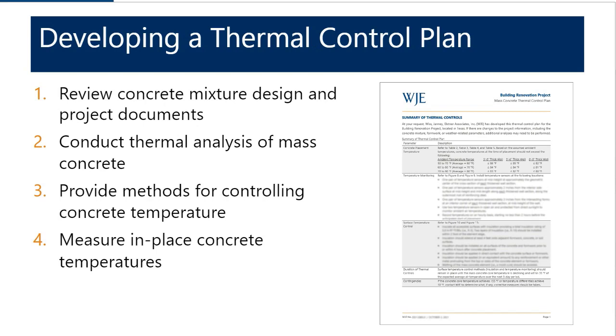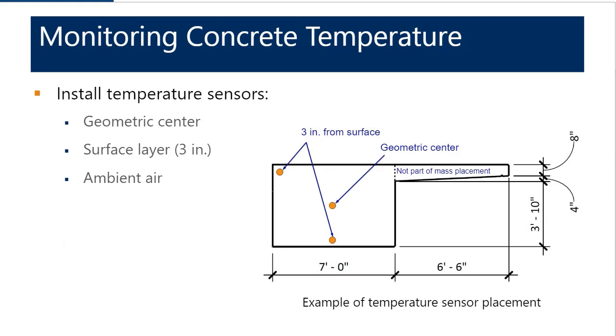The last portion of developing a thermal control plan is to develop methods for measuring the in-place concrete temperatures. Monitoring concrete temperatures is performed using temperature sensors, and typical placement for these temperature sensors is at the geometric center of an element or at the location where you expect the highest temperatures to be achieved. Usually this is the geometric center, but sometimes, depending on if the element has blockouts or other features, it might be a little bit offset. So you want to install a sensor at that location.